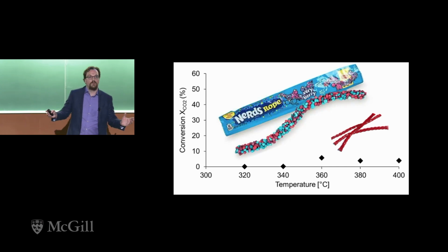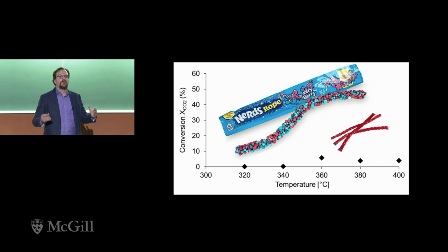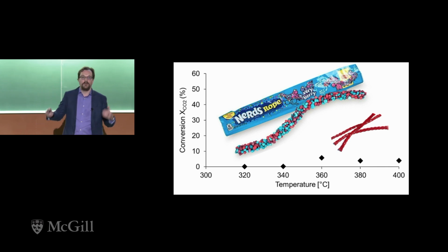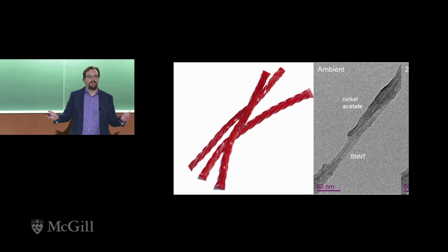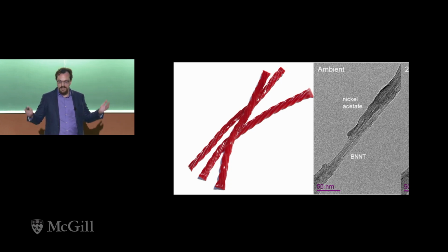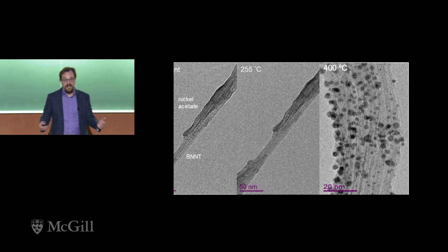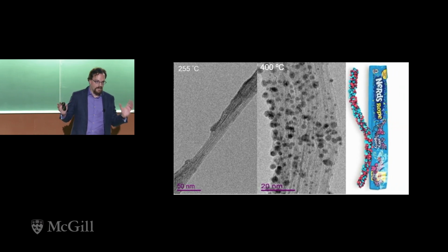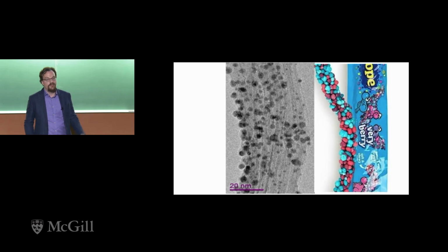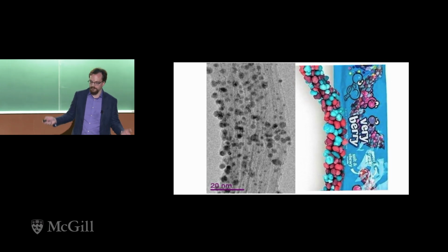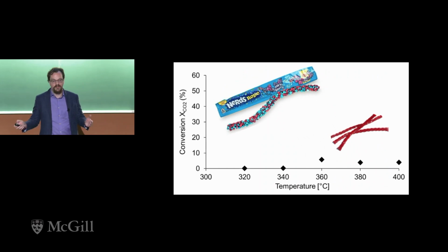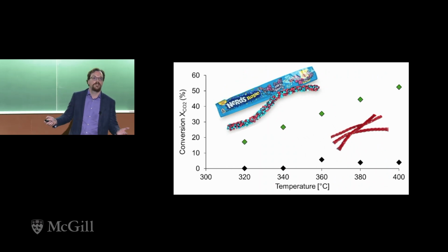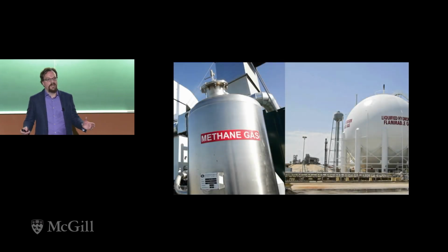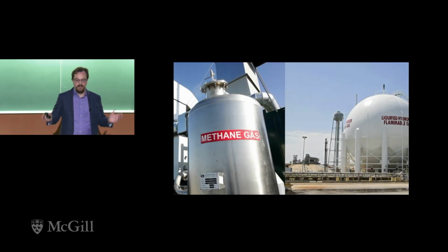So the reason this works is small metal particles increase the surface area of the catalyst, which therefore increases conversion. Now, to figure out if I can do this, using an electron microscope, I pipetted nickel acetate onto a nanotube, and I raised the temperature to 400 Celsius. And as you can see, the metal particles started to look a lot like the nerds on the Twizzlers. So I tested it again. And what I found is that the CO2 conversion increased up to 50%. So what I'm hoping is I can use this catalyst one day to convert green hydrogen into methane as a long-term energy storage solution. Thank you.